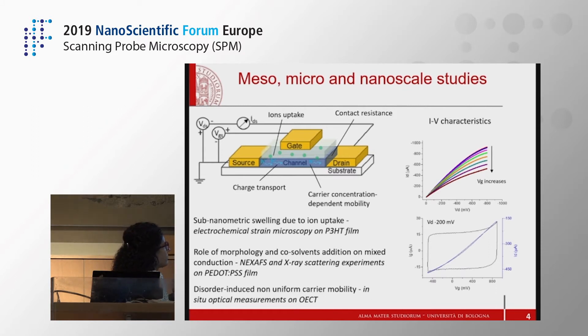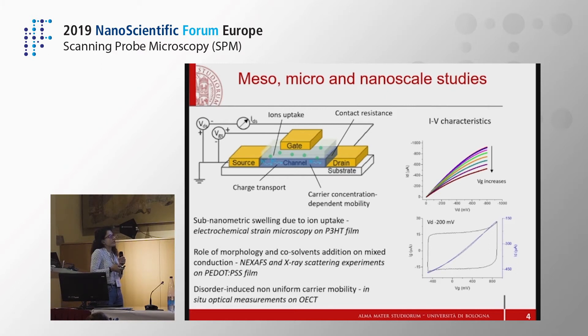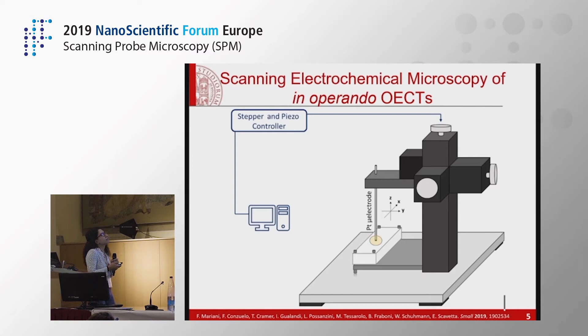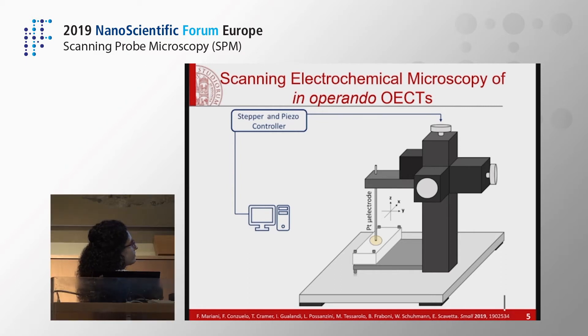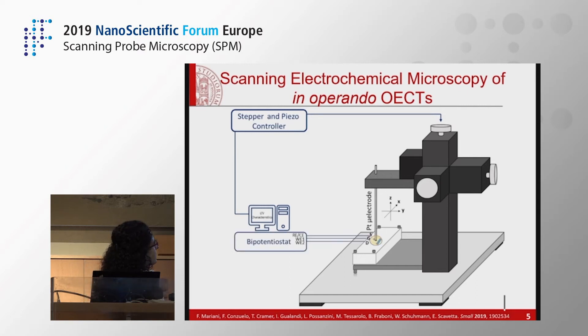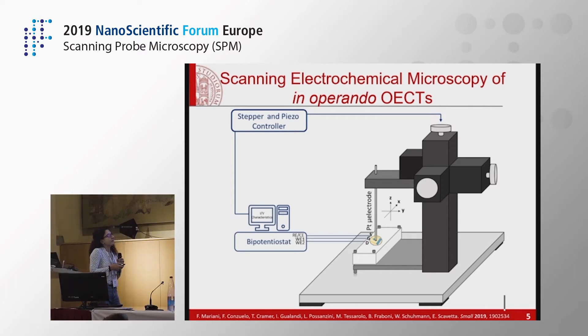The aim of this work was to provide a tool to characterize organic electrochemical transistors in operando using an electrochemical probe. We made use of scanning electrochemical microscopy (SECM) in a traditional configuration. Our electrochemical probe was a platinum microelectrode controllable in three axes. The substrate was the organic electrochemical transistor under study, controlled by a bipotentiostat to apply gate and drain potentials while recording the generated currents. A quasi-reference electrode — a silver wire — was used to record the SECM probe signal.